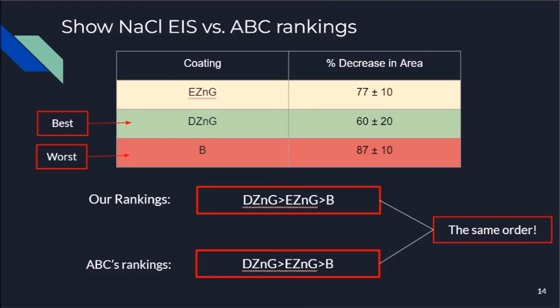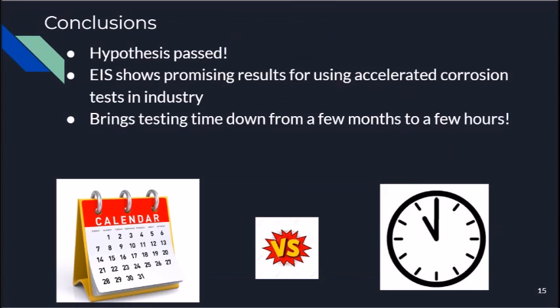So ranking the three coatings, we had the zinc dip spin coating performing the best with the smallest area, followed by electrogalvanized zinc, and our black top coat performing the worst. And when comparing this to ABC's rankings, we see that the rankings are the same, which is a good sign for our testing. So in conclusion, our hypothesis passed because our rankings were the same, so our EIS shows promising results for using accelerated corrosion tests in industry, which brings our testing time down from a few months to a few hours. Thank you for listening to our presentation.